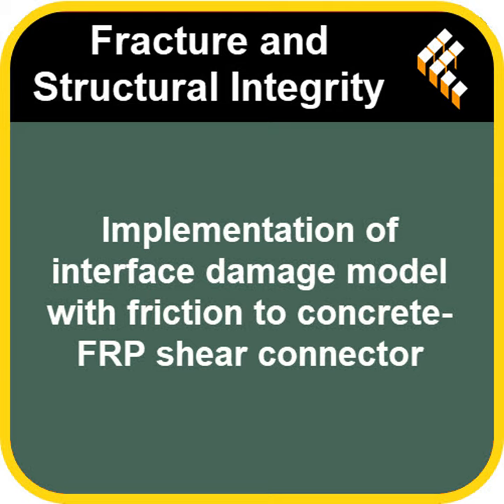It sounds incredibly detailed. So modeling these tiny interfaces, especially with friction after debonding, how do they actually simulate something that complex? What's happening inside their computer model? It's pretty sophisticated stuff. The researchers developed their own computational code in MATLAB. The basic idea is modeling that interface as an adhesion zone. Degradation leads to debonding, yes, but, and this is the key insight they build on, even after debonding, the surfaces can partially stay in contact. And this leftover contact is where friction comes into play, and it significantly changes how load gets transferred and how the structure behaves after that initial damage starts.